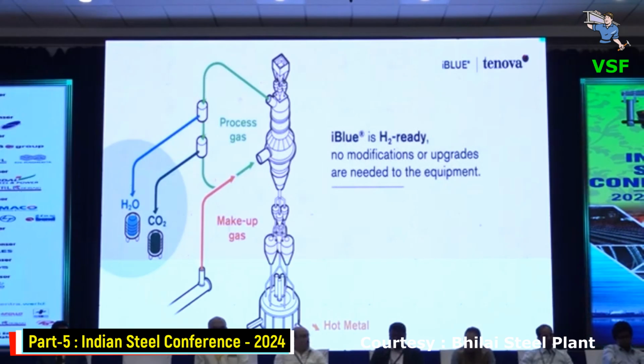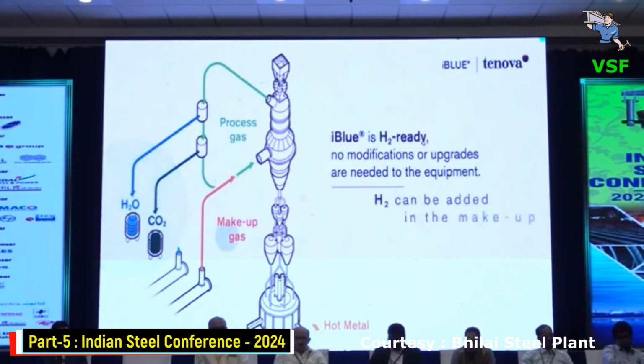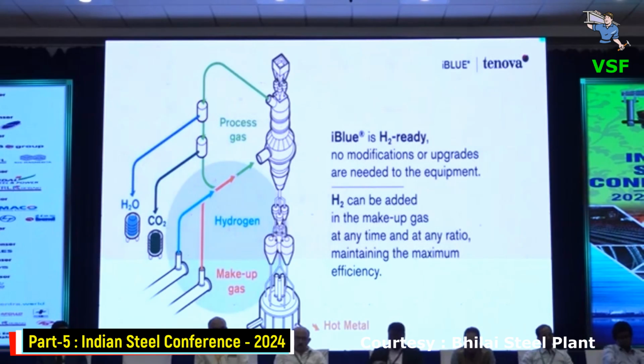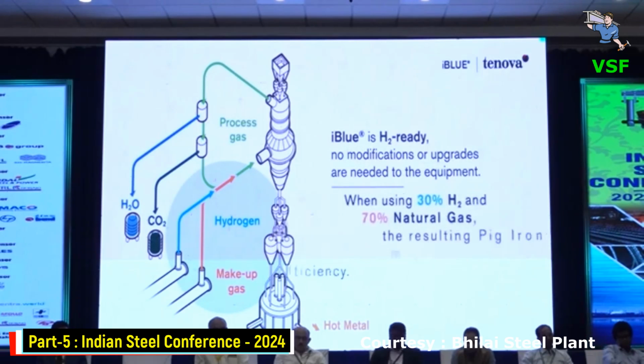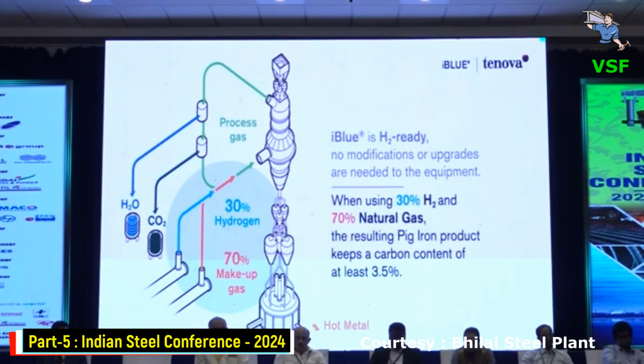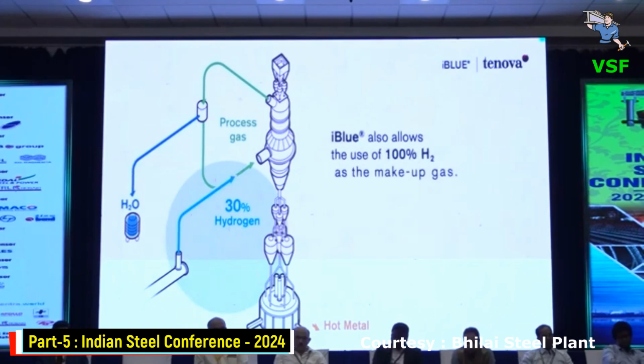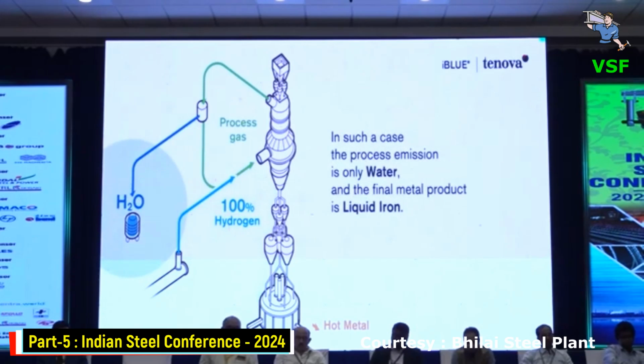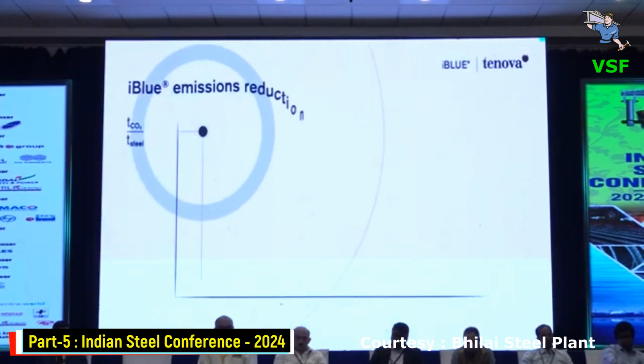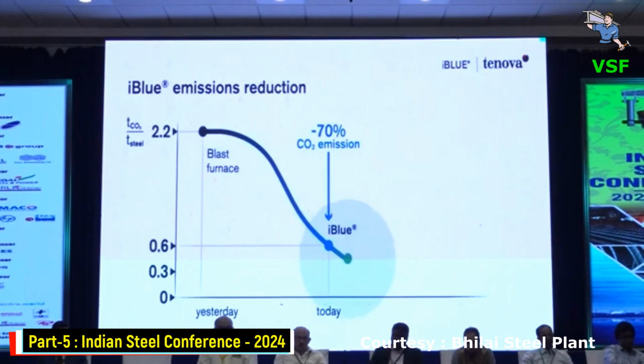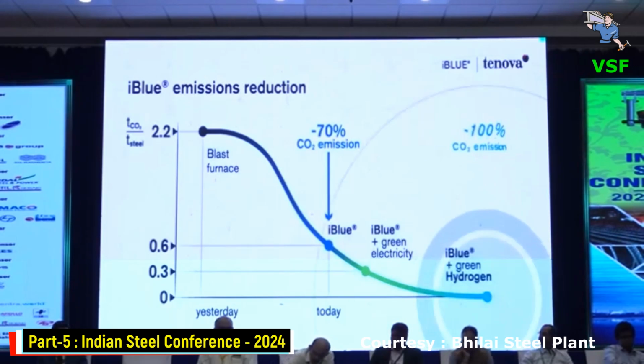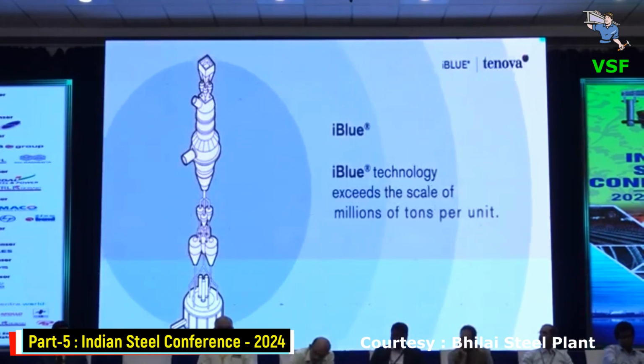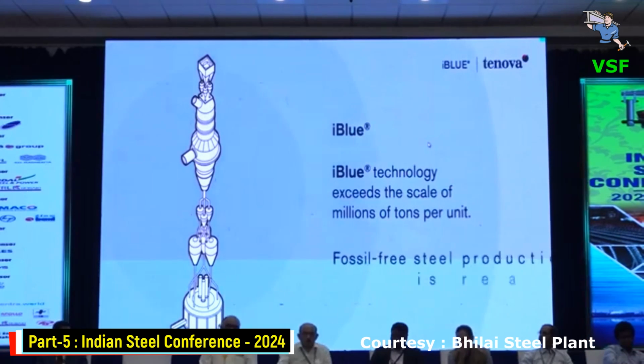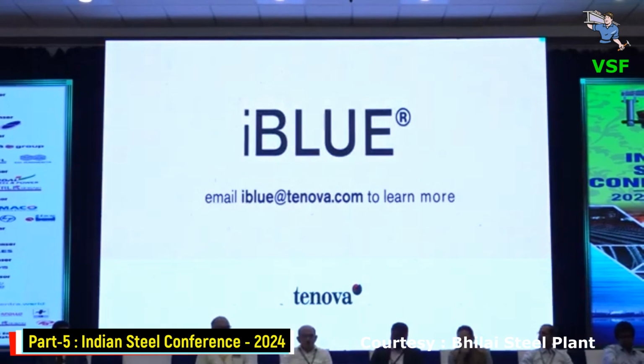iBlue is H2 ready. No modifications or upgrades are needed to the equipment. H2 can be added in the makeup gas at any time and at any ratio, maintaining the maximum efficiency. When using 30% H2 and 70% natural gas, the resulting pig iron product keeps a carbon content of at least 3.5%. iBlue also allows the use of 100% H2 as the makeup gas. In such a case, the process emission is only water, and the final metal product is liquid iron. iBlue technology exceeds the scale of millions of tons per unit. Fossil-free steel production is real. Tenova.com. Thank you.